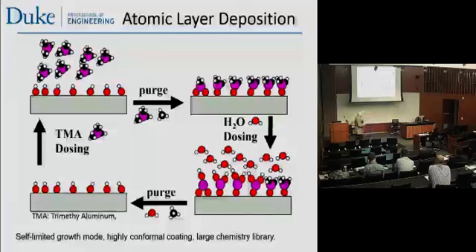Now, that does limit what surfaces you can grow on. So that's where the expertise comes in: can you grow on this surface, or do you treat that surface first, and can you grow this conformally? But as a technique, it's become very popular with a number of different industries because of its conformal nature. You can imagine if you have a nanostructured material, in energy for example, but you need a very thin, ultra-thin layer on it, how do you get the material in there? Well, atomic layer deposition is one of the very few ways that you can do that. This is done in a vacuum with chemical vapors, and you can also do it electrochemically as well.